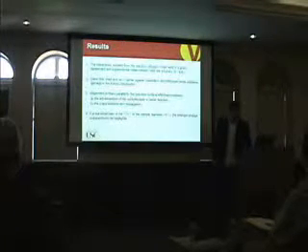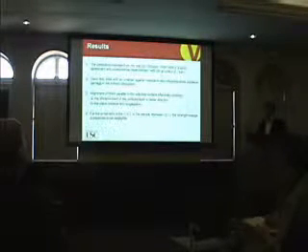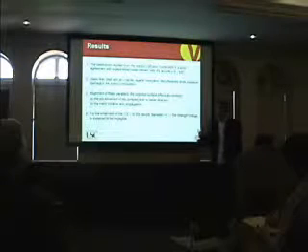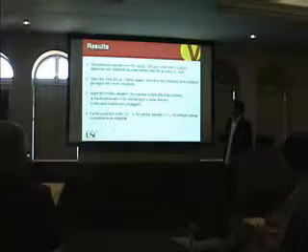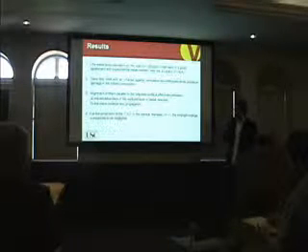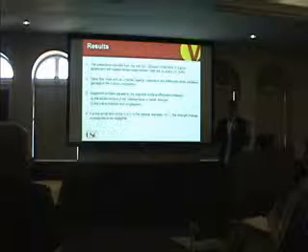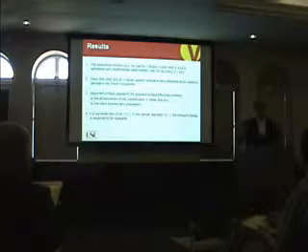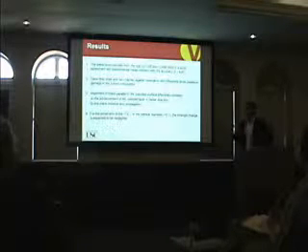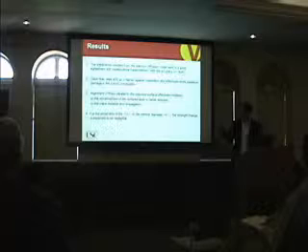And as a conclusion, we used the diffusion reaction equation to model our system, and it really works up to a certain time. The glass fiber also acts as a barrier against oxidation of our carbon core, because our carbon core has more strength and mainly reinforces the material.